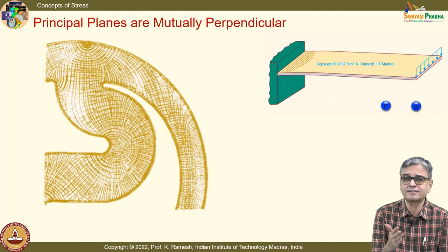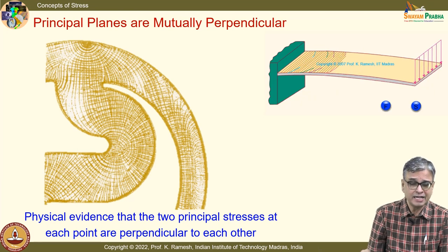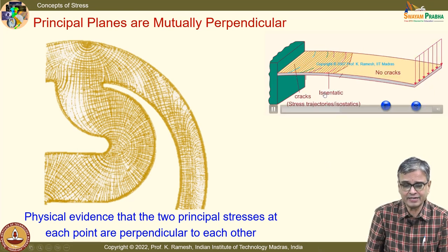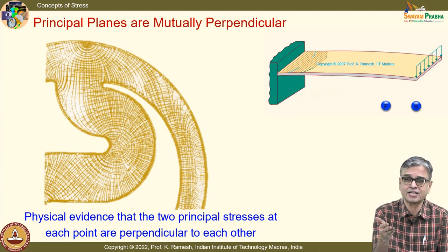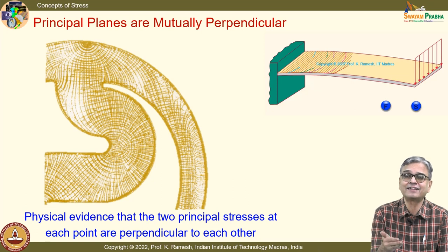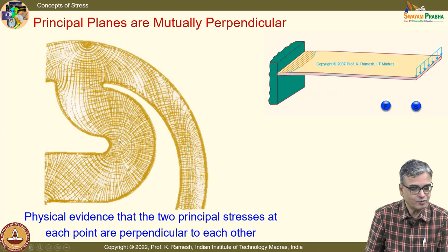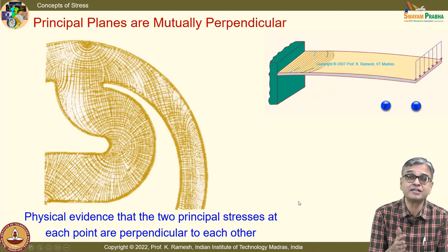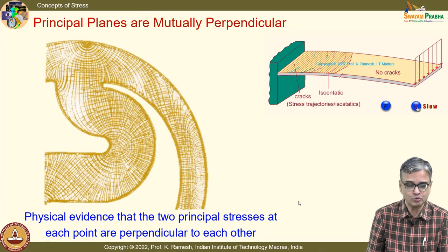When you do this as an Eigenvalue-Eigenvector problem, the Eigenvectors are mutually perpendicular mathematically. There is also an interesting experimental technique where you coat the specimen with a brittle material; when stresses increase, it fails by maximum normal stress, indirectly giving the direction of the principal stress. A careful experiment by Professor Durelli showed two families — one like circles and another like radial lines — establishing experimentally that principal planes are mutually perpendicular.